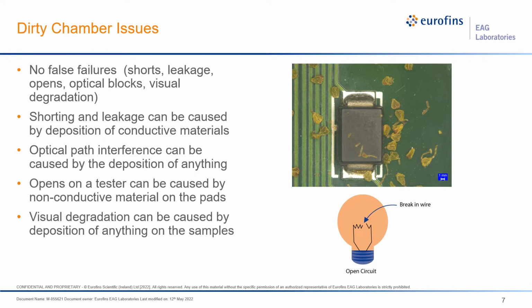The optical path interference is particularly difficult because anything that gets in the optical path of your LED for light output or your sensor for light input will reduce the sensitivity or the output. Opens actually don't have to break something in your sample. It can just be some sort of non-conducting material that covers the pads, which causes the testers later on to have an issue where they get high resistance or a non-contact. Also, visual degradation: if you're making parts that have to pass a visual, if they've got some sort of haze or a film put on them, that won't work very well.